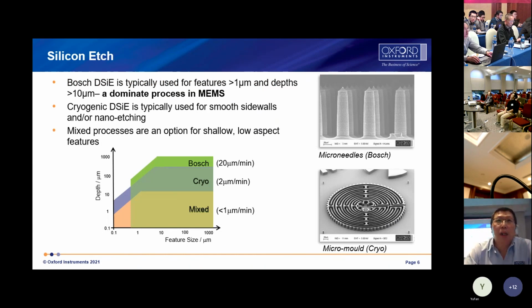Silicon can be etched by any halogen atoms, but only fluorine reacts with silicon spontaneously. That means we need a passivation to maintain a vertical profile. I believe you all know the Bosch process. The Bosch process uses an alternating sequence of deposition and etch. In the three-step Bosch process, the first step is deposition, then a breakthrough step removes the polymer on the bottom but keeps polymer protecting the sidewalls. Then isotropic etch last, and the cycles repeat to etch deeper.